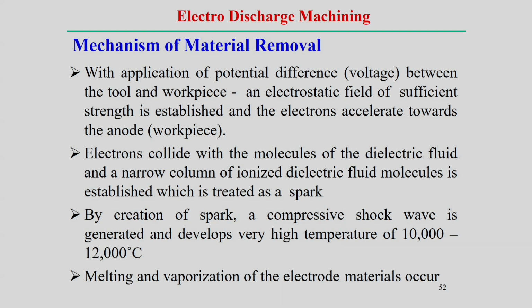Mechanism: if you look at the mechanism of material removal in the electro discharge machining process, we can see the voltage between the tool and the workpiece is applied, and that creates an electrostatic field. When the field is of sufficient strength, electrons are accelerated towards the anode, which in this case is the workpiece. Once electrons collide with the molecules of the dielectric, of course, in between there is a dielectric fluid, they create a narrow column of ionized dielectric fluid molecules, and then that narrow gap tries to establish the spark.